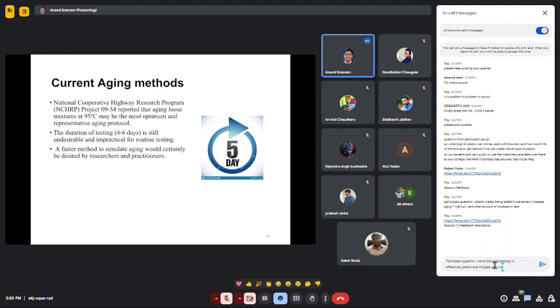Asphalt mixes and pavements are designed for 10 years or 20 years. We cannot wait 20 years to see how our material will behave, right? We need to understand today how our material is going to behave 20 years in the future. And one of the ways we can do that is to simulate aging in the lab. Different people have developed different methods. One of the main common methods is from the US. It reported that we can age loose asphalt mixtures at 95 degrees for about 5 to 6 days in a laboratory. And this would be the way to simulate how these materials degrade over maybe 10 years.